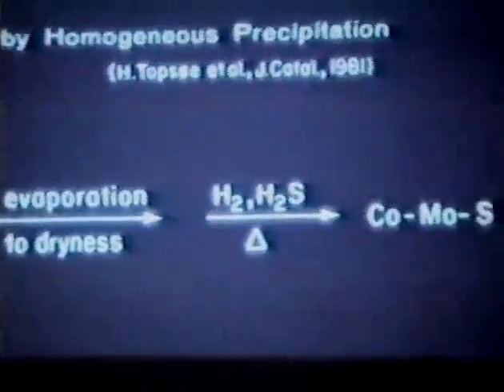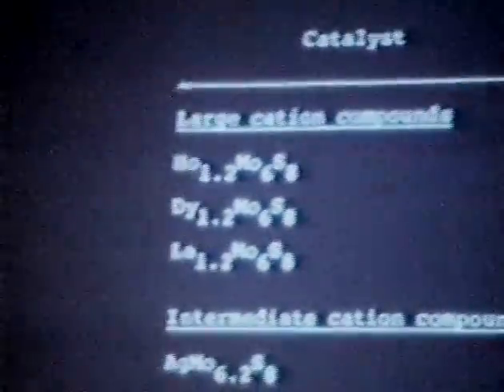Well, let me tell you a little bit about the characterization of the Chevrel phase materials. As I mentioned, they're low surface area materials. Using this classification of large, intermediate, and small cation compounds, the fresh materials usually have surface areas less than about 1 square meter per gram. This may change a little after they're used in thiophene hydrodesulfurization for 10 hours. Some show increases, and for some there is not much change. Again, the compounds that we're comparing here are of higher surface area.